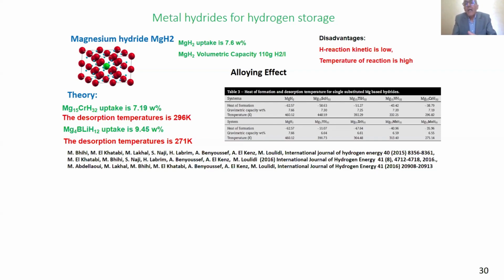But there are two disadvantages of this material. The kinetics is low, and the temperature of reaction is high. There is a need to improve the kinetics, reduce the time of absorption and desorption, and reduce the temperature of desorption.